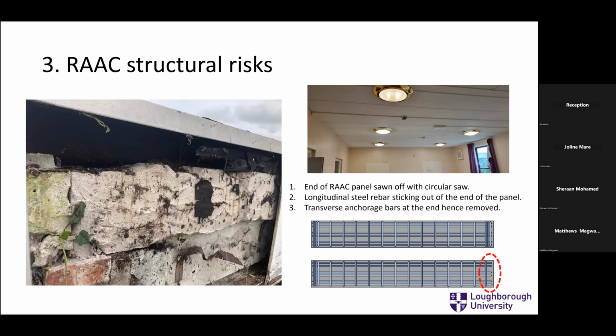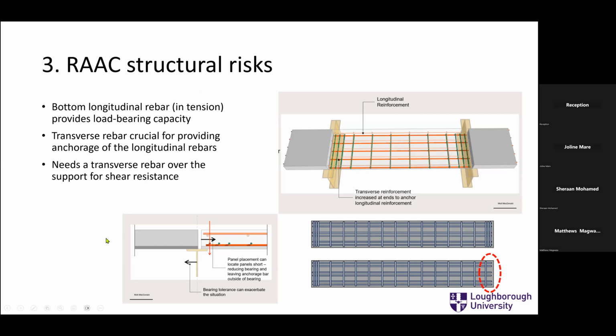This is where builders have cut the reinforcement off, which in any type of concrete is obviously a bad thing to do, but in particular for RAAC is very bad. So there's a photo of the inside of a RAAC panel. You've got the longitudinal reinforcement and transverse reinforcement. And it's the last bar that's important. You need that anchorage bar at the end to anchor at the end. And it's this zone near the support that we're worried about.